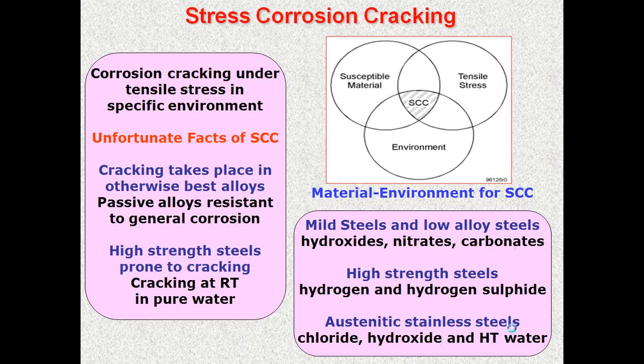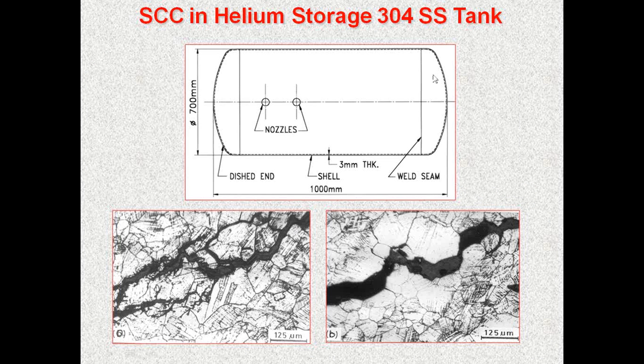This is a typical example of a storage tank for helium gas made of 304 stainless steel. You see where there is a weld seam here, and after the weld it underwent a hydro test to see the leak proof, and then the workers left some water which was not drained completely after the hydro test.